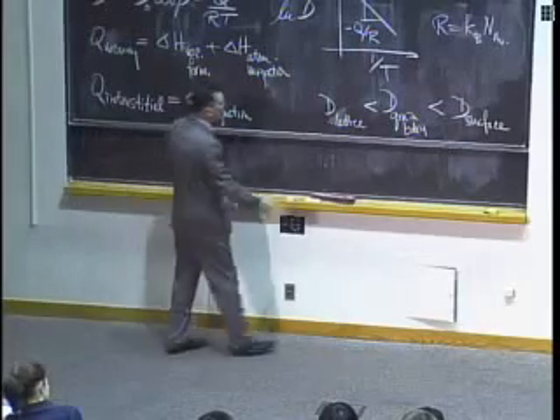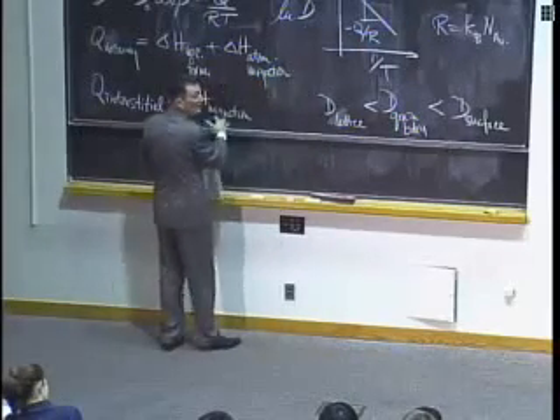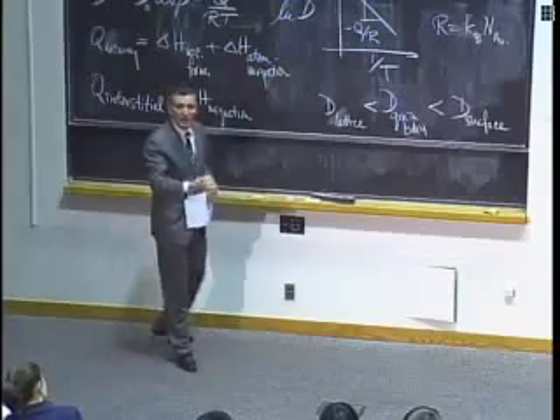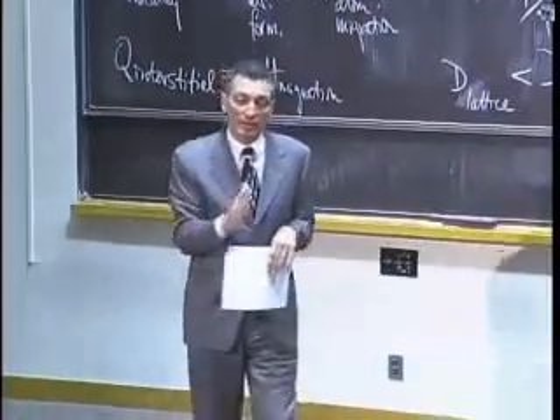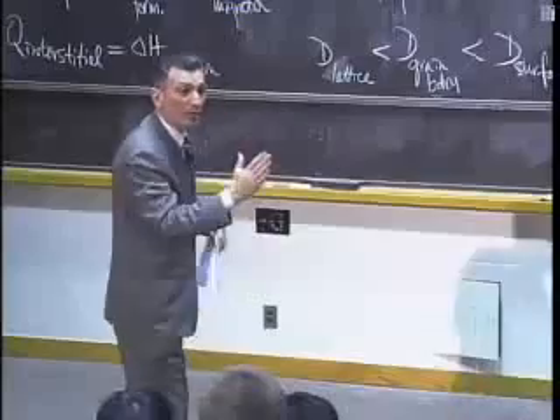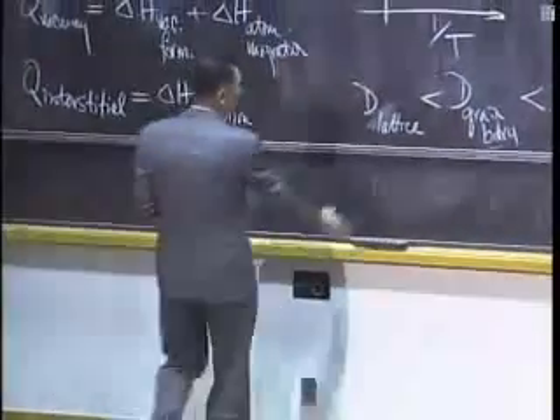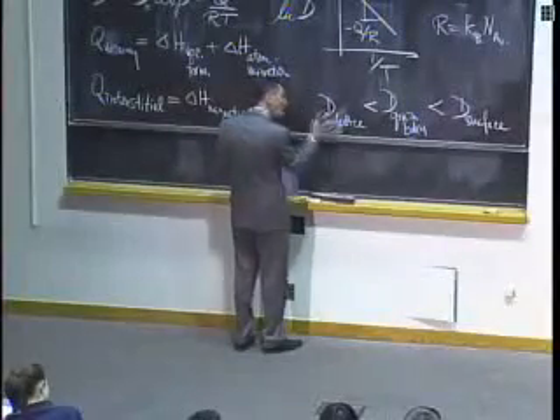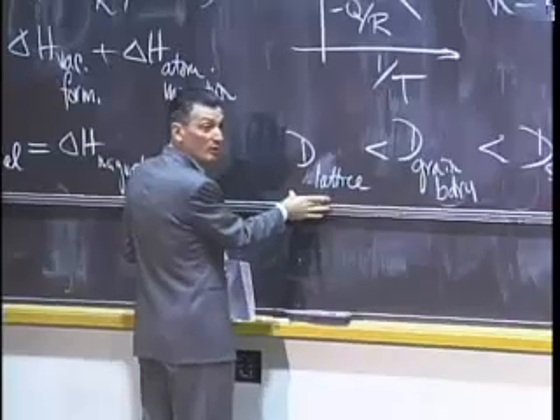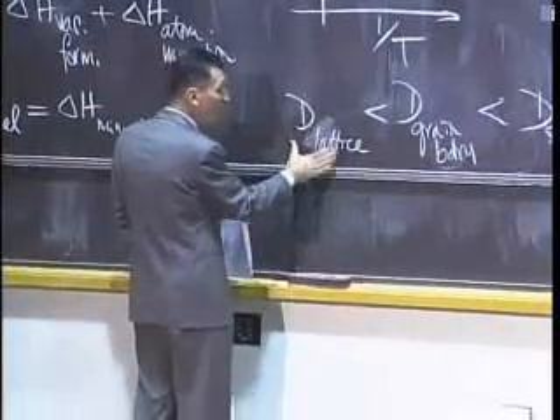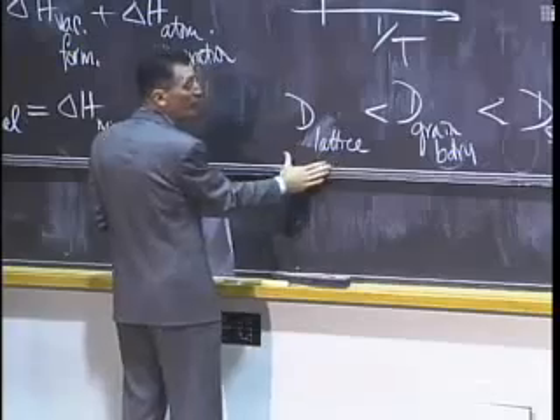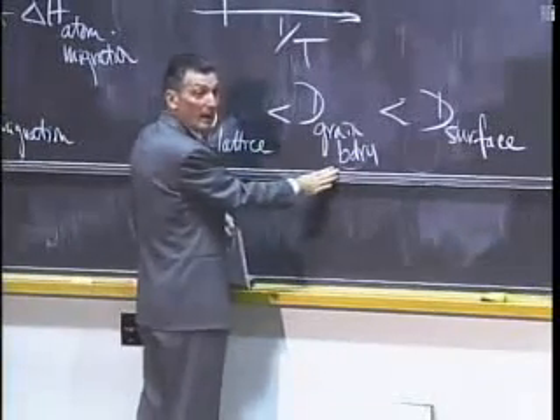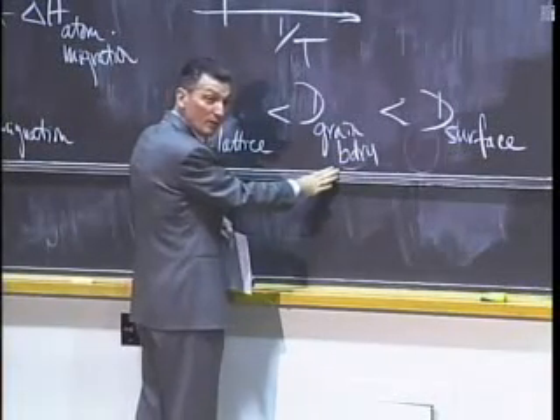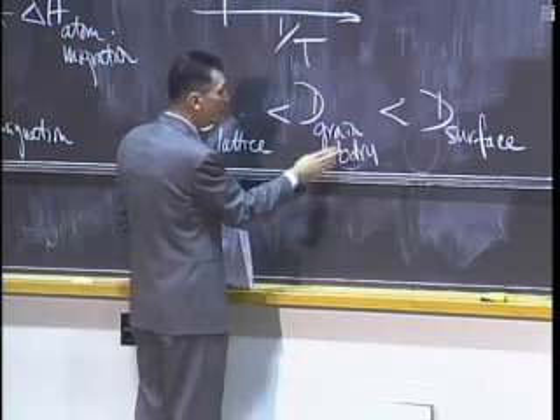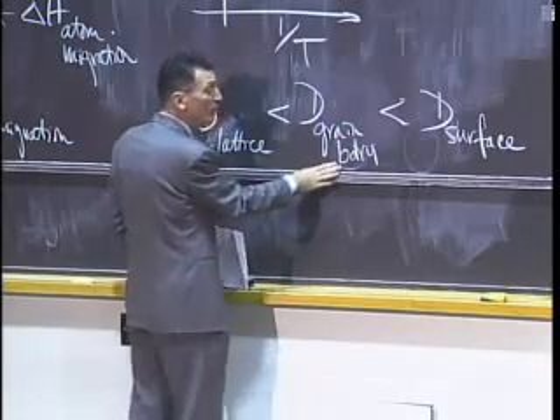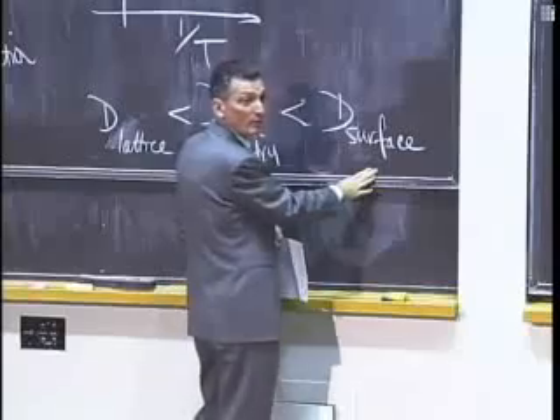And then lastly, we looked at how these two are related to the degree of confinement. In other words, the atom is restricted by the ease with which it can run down its appropriate raceway, and we reasoned that going through the bulk lattice is the most tortuous path and has the highest activation energy, lowest diffusion coefficient. Grain boundaries have atoms with fewer nearest neighbors, a lower coordination number, so the diffusion coefficient is higher in the grain boundary, and it is highest along the free surface.